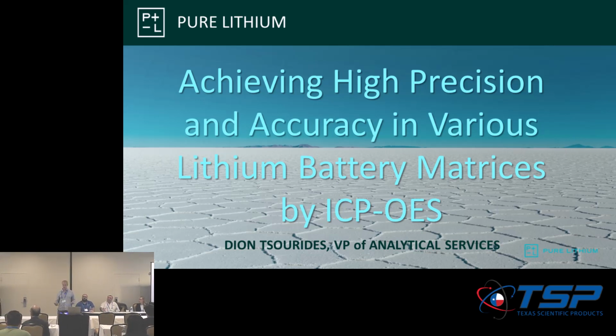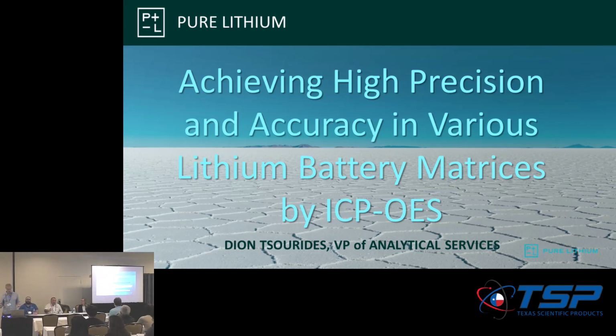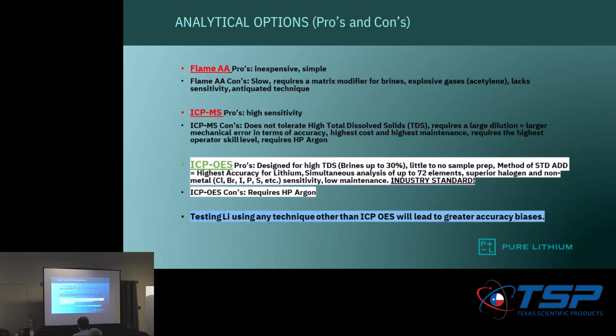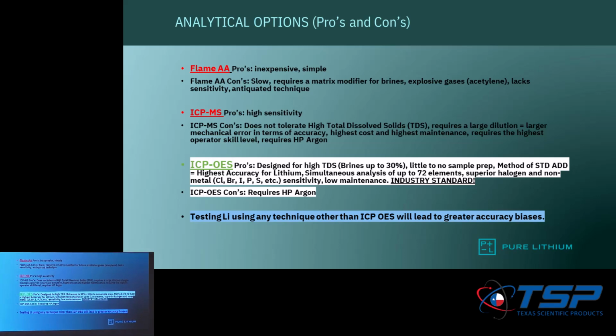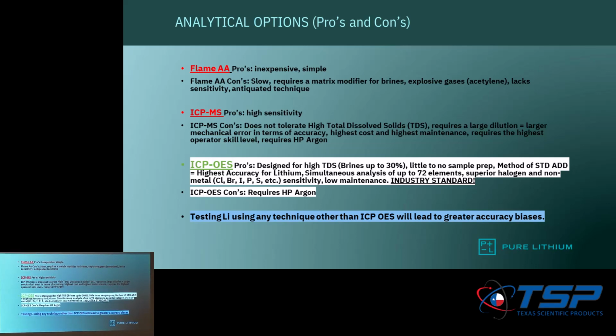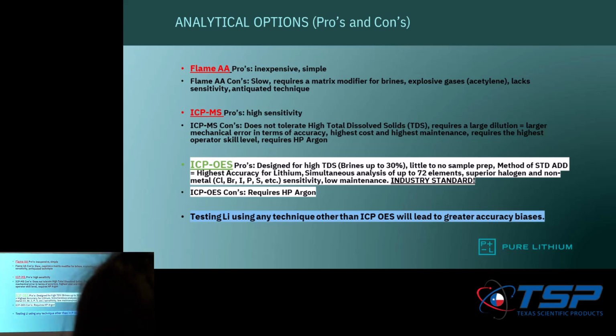You really have 3 ways to look at the sample: AA, mass spec, and ICP-OES. You can use AA. It's an antiquated technique. It is inexpensive, but there are some issues with safety, and it's not truly going to provide the performance we need for our needs. We need the halogens as well. One of the reasons for that is chlorine. We don't want lithium chloride as any of the lithium form of the raw material we're working with.